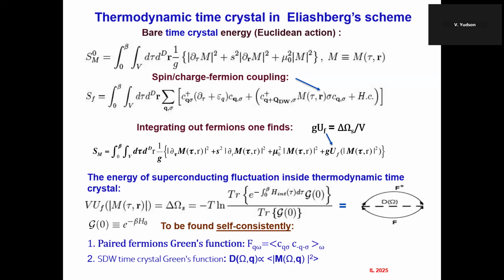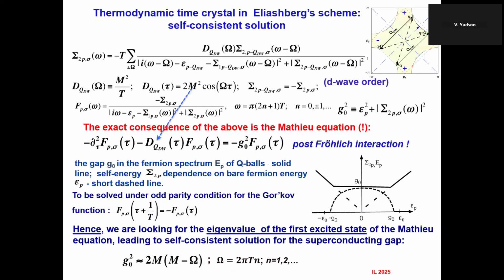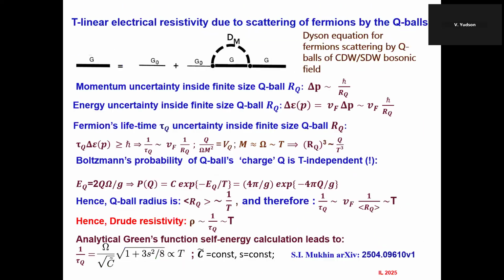But what is also interesting is that if this M is a charge density wave amplitude, then this sigma is not here. We know that when you decouple the Hubbard Hamiltonian with Stratonovich fields, there is a term also without sigma. Then, in order for this loop to be negative, you should have S wave. And indeed, experimentalists now say that they have seen both S wave and D wave kinds of superconducting behavior in high Tc cuprates. So it's funny, but this simple derivation also explains why it may be so.